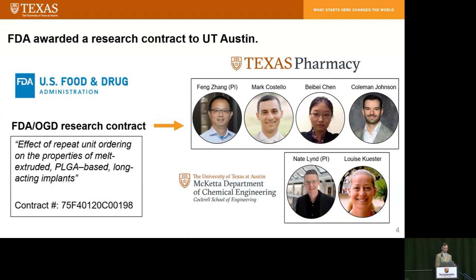Over the last 6 years, we researched this topic at UT Austin. This was a collaboration with the FDA via a research contract, which was titled Effect of Repeat Unit Ordering on the Properties of Melt-Extruded PLGA-Based Long-Acting Implants. The key term here is repeat unit ordering. This refers to the fact that PLGA is a copolymer, and the sequence of monomer units in the polymer chain has a significant effect on the behavior of PLGA.